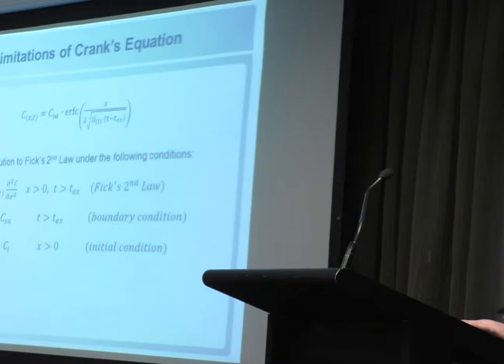this error function solution is only a genuine solution to Fick's law under certain boundary and initial conditions. And the principal boundary condition is that the surface chloride concentration stays constant over time. So if that isn't true, these models are completely invalidated. And that sent us back to the literature to look for a solution. And it does turn out